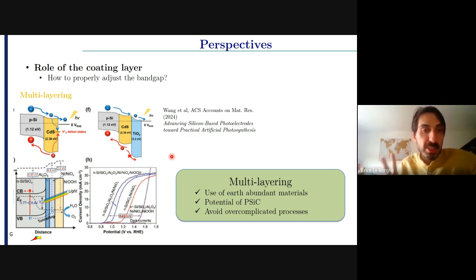So there are basically two possibilities. Either you do multi-layering, so you could add a layer with an intermediate band gap between the silicon and the titanium dioxide, so it helps the electrons to flow, and it's much better. But of course, when you check these kinds of materials, they are not always earth abundant, or they can be toxic. I had the discussion with some people before. They would say that cadmium based materials are not toxic because they are encapsulated and so on. Fair enough, but still I think if we can avoid this, it's better.